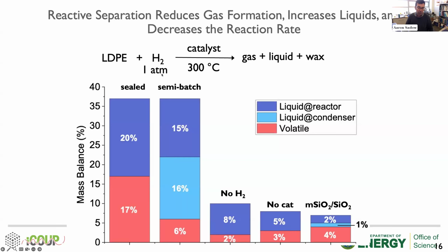So we're doing this now at very low pressure, just 1 atmosphere of hydrogen, and we can compare the conversion and the selectivity. At 1 atmosphere of pressure, the catalyst in the sealed reaction makes really a lot of gases. At this conversion, about 50% of the mass is going to gases, because the small molecules are trapped in the reaction mixture and can get back and get recleaved. In contrast, in the semi-batch system where we allow the volatile species to escape, we get much less gas at the same conversion, and we're instituting this so-called reactive separation that gives us the products directly. So you no longer even have to extract them out. They come in the form in which they're made by the catalyst.